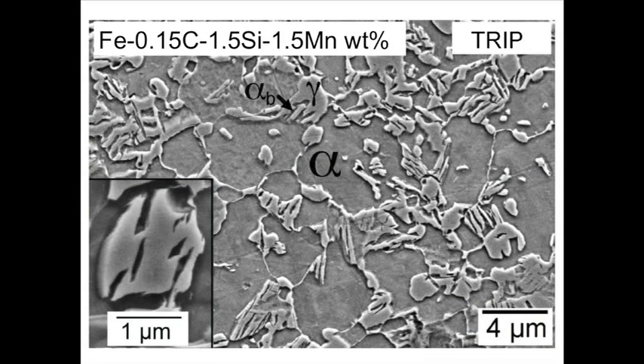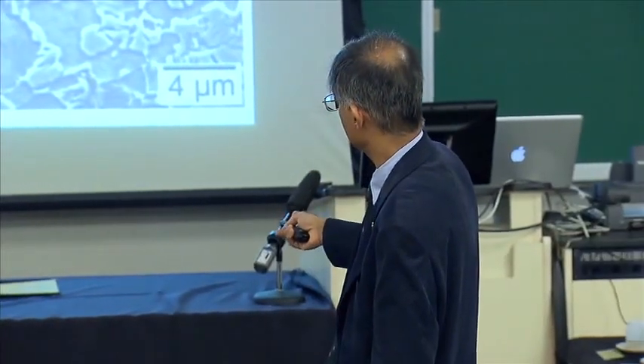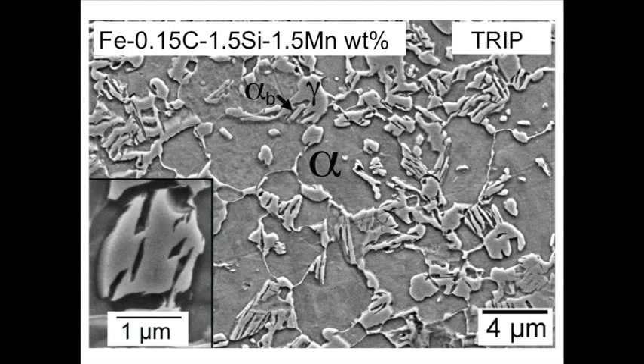So notice that the carbon concentration is very small. So how do we stabilize the austenite? If I quench this material, it would transform completely into martensite. There would be no austenite left. So what they do is they first form about 70% of ferrite at a high temperature. When the ferrite forms, it partitions carbon into the rest of the austenite. So even though your average carbon concentration is 0.15, the concentration in the austenite is much greater. And you increase it further by transforming at a lower temperature into bainite, which also partitions carbon. So you end up with about 1.28% of carbon inside the austenite, even though the average is 0.15.